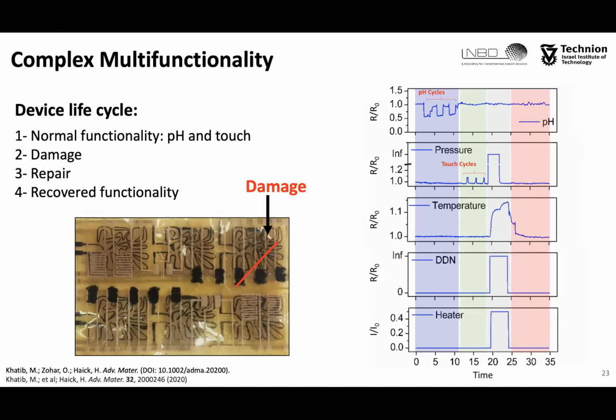In the case of small scale damage, below 100 micrometers in depth, the intrinsic self-healing capability operated alone for recovery. However, once the damage is large enough, above 100 micrometers in depth, both the intrinsic self-healing and the self-repair mechanism could operate until we got complete recovery.